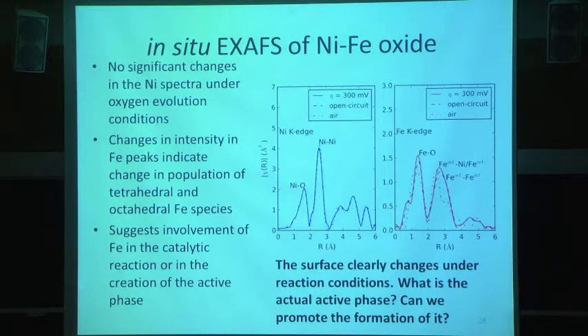Now this doesn't tell us a whole lot, and so we had this result. We know now that iron is involved in the oxidation of water, that it's changing the surface. This is clear evidence the catalyst is changing under the oxygen evolution conditions. And so now we're going to start thinking about the actual active phase of the surface. Maybe it's not nickel oxide at all. Maybe it's not even the nickel iron spinel. Right? We can't really tell from what I've shown you so far. And so if we could identify this actual active phase, then we might think about how to promote the formation of it. And so that's what I want to finish the last part of the talk with.